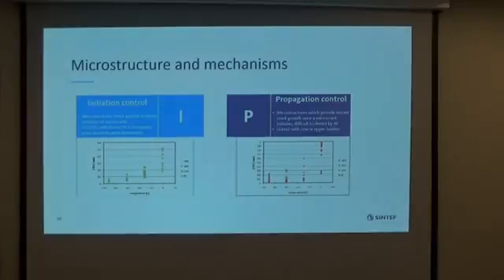And the second one: in order to understand why the scatter is there, we do a lot of testing and also simulations to understand the microstructure and the link between microstructure and the failure mechanisms. So we propose initiation control or propagation control mechanisms by using acoustic emission. We have to listen to the material. If your material broke at minus 16, what sort of acoustic emission signals can be detected? And indeed, we can roughly link this CTOD value with different microstructures.